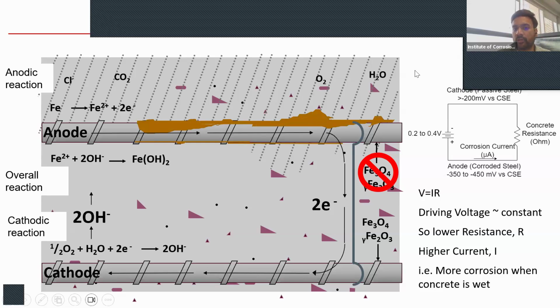So if we see a typical circuit diagram of this corrosion in concrete, we have a passive steel in the concrete and an active steel. The potential of the active steel is higher, more negative than the passive steel. As a result, the corrosion current flows.